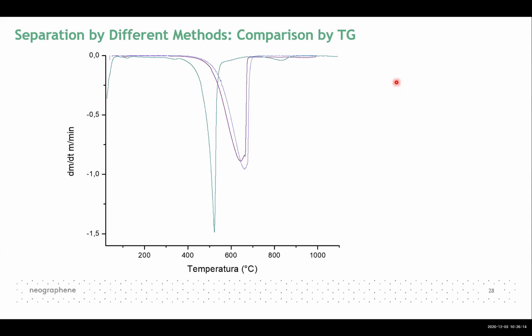For example, when you look at the TG, the thermogravimetry, if you change a little bit the separation, you go from a burning temperature around 600 to a burning temperature very sharp at 540. What does this mean? This means that you can customize the graphene. Of course, here we have 0.2 grams per liter. But this might be good for some kind of applications. Here we have like 0.7 grams per liter, and this will be nice for some kind of application. So this means that we can modify the material, we can customize the material, and this we will work constantly with our customers, with the companies, with the research institutes that are working with us. Okay.